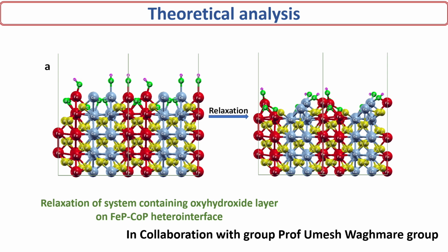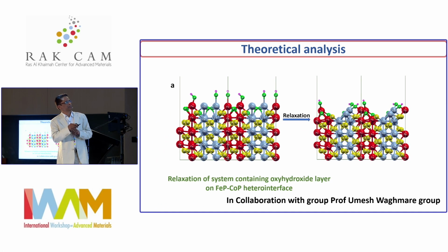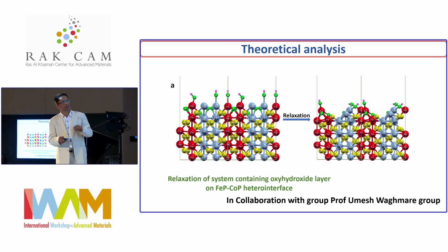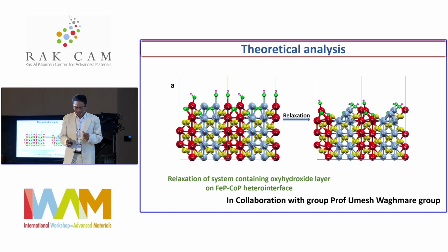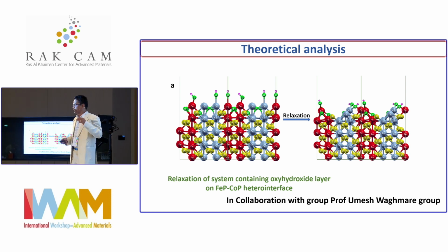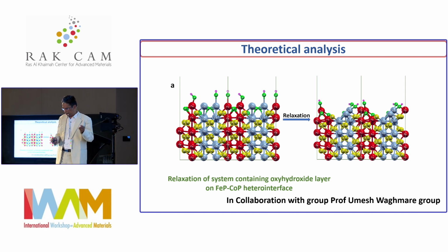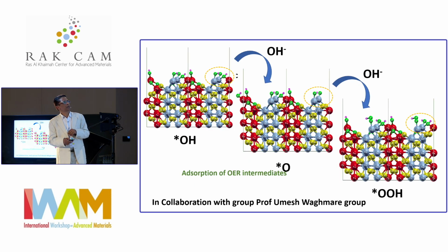And with Professor Umesh Waghmare, we have calculations on how this active site works, since our analysis shows the formation of oxy-hydroxide surfaces post-reaction. So he created the surface models of the phosphides. The surface was changed with oxide and hydroxyl groups, allowing relaxation to get the structure without much modification. And then we look at the Gibbs free energy of intermediates in each reaction step, the Gibbs free energy of adsorption by attaching the oxygen, OH and OOH groups at each site.